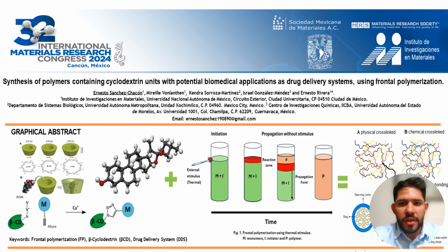Frontal polymerization is a process to convert a liquid monomer, generally, into a polymer by a localized polymerization reaction, which is initiated at one end of the system using a thermal or photochemical stimulus. This stimulus can create a thermal wave that advances frontally, where the initial energy created is the only energy required to initiate and terminate the polymerization process.